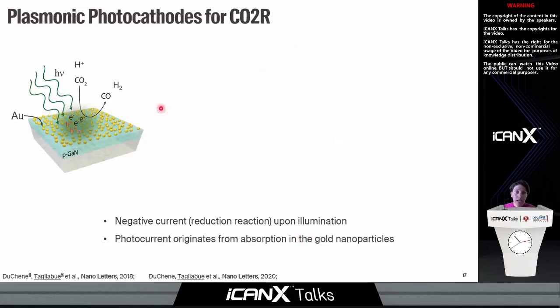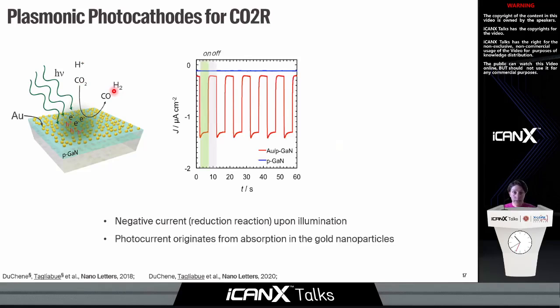So indeed, we took an analogous sample. Again, we have these gold nanoparticles on p-type gallium nitride. We inserted it in a photoelectrochemical cell, and we studied the reduction reaction of CO2 to CO and hydrogen evolution. And we do this as a function of photon wavelength. So the first thing that we see is that every time we illuminate our device, we see an increase in the current that is generated. And this is a signature that indeed we are increasing the reduction reaction.